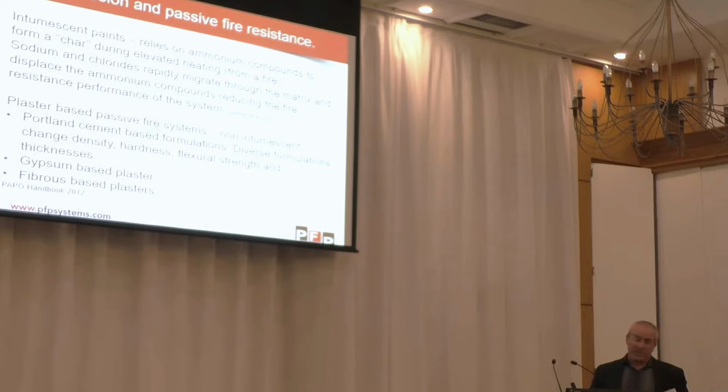The density, for example, of normal cement for a 50 mm layer could be around about 125 to 150 kilograms per metre squared. These can be reduced with additions of products like vermiculite and perlites, additives, and various other permitted flavourants and colourings, to around about 25 to 50 kilograms per metre squared.